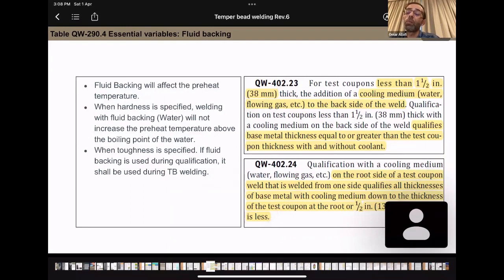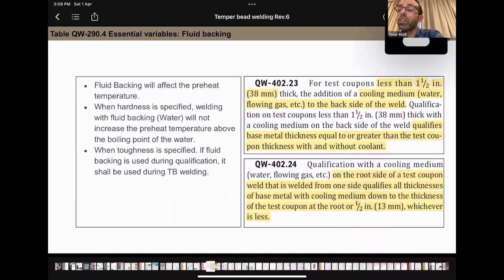So this is more difficult when it comes to hardness. When you qualify using a cooling medium, you can be qualified for welding without a cooling medium. It's exactly the opposite when it comes to toughness. On the toughness side, when you are qualified with a cooling medium, you cannot do the welding without a cooling medium in the WPS.